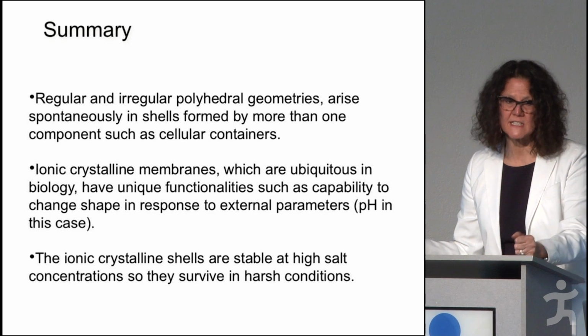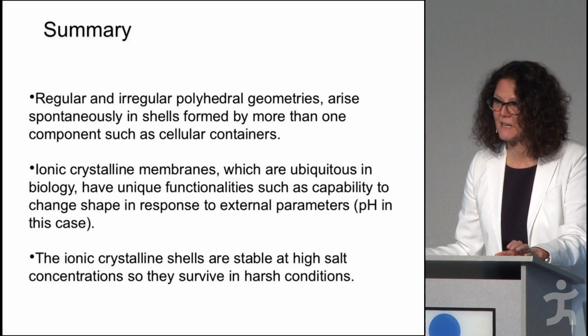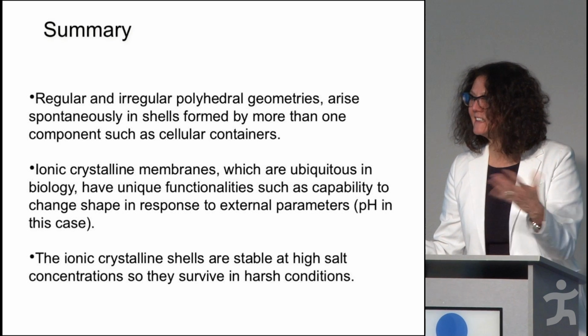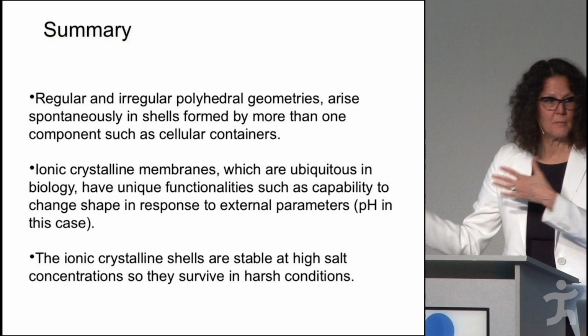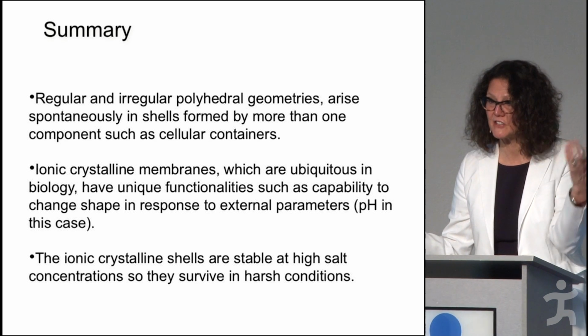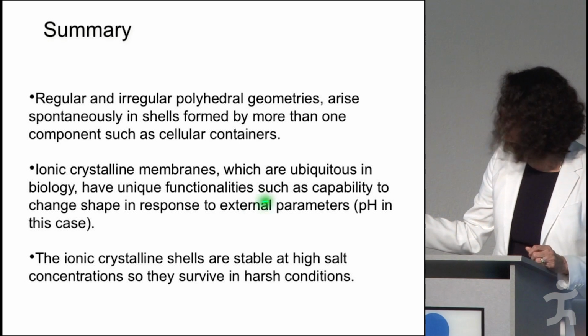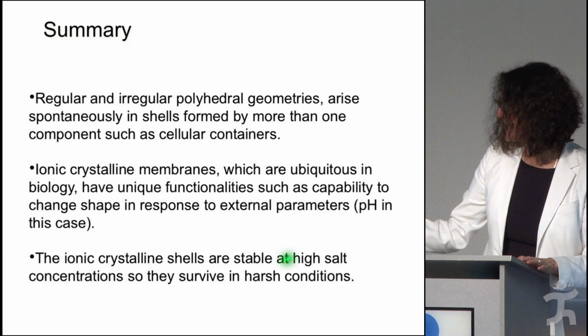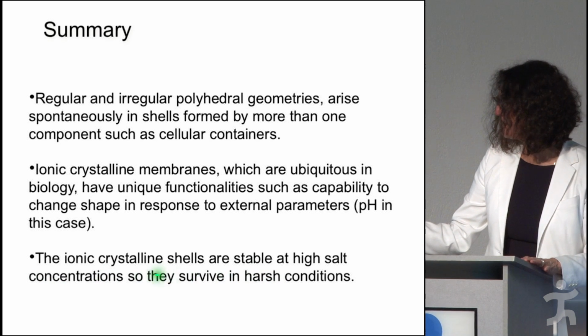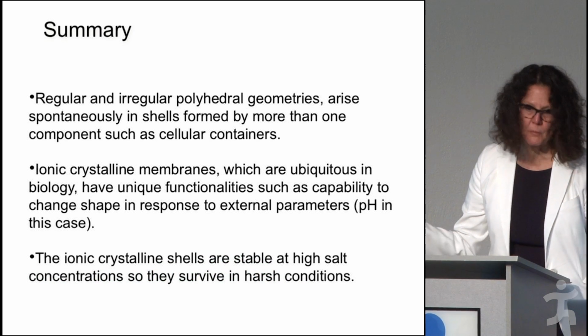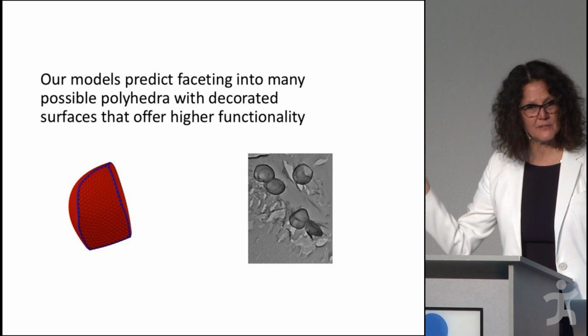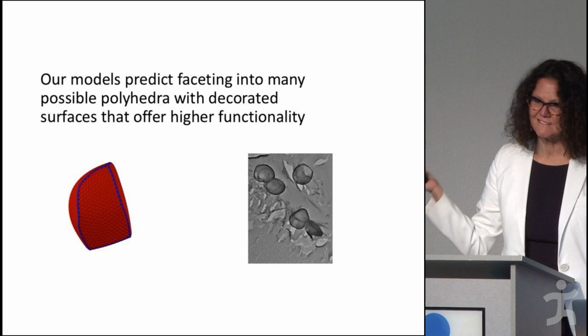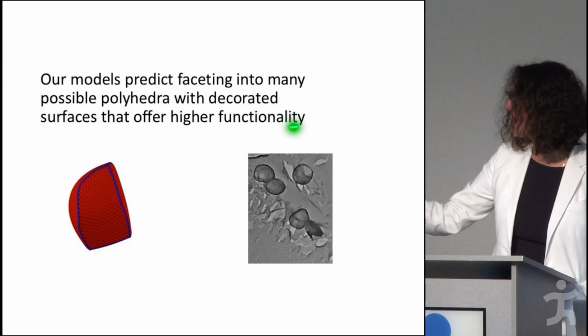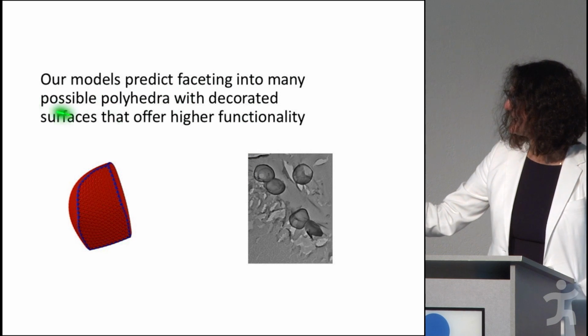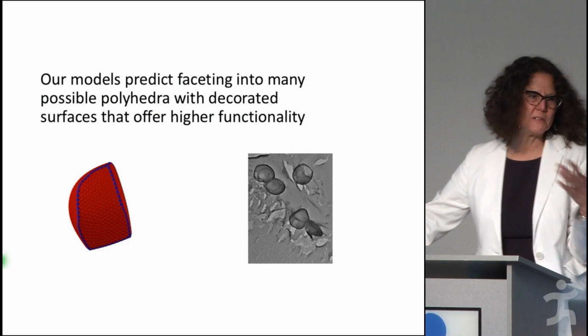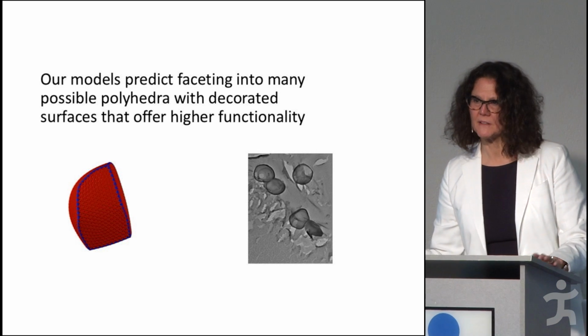Like if you have an ionic bonding, it's 100 kT. You don't change that, right, in a ceramic. But if it's 10 kT, 5 kT, and thermal energy is 1 kT, you can actually undergo many processes, and that's why we're so functional and can change and be soft and so on. And the ionic crystalline shells are stable at high salt concentration, so they actually can survive in harsh environments. Interesting is they survive at high salts, but not by changing the pH, which is a different functionality. And so our models were able to predict this faceting, and I showed you that these decorated polyhedra arise by the continuum model and also by the molecular models in the system.